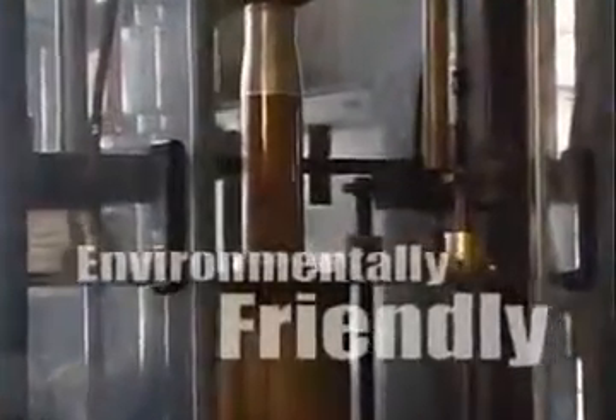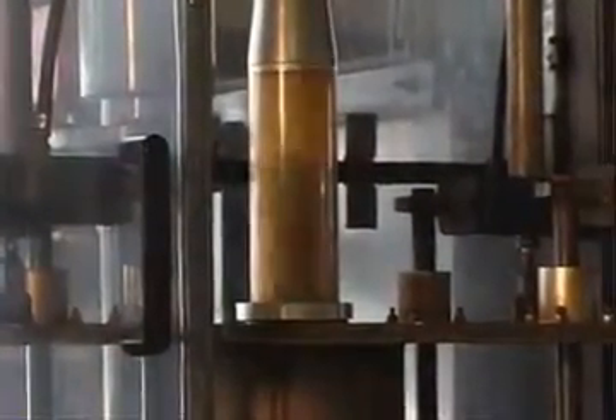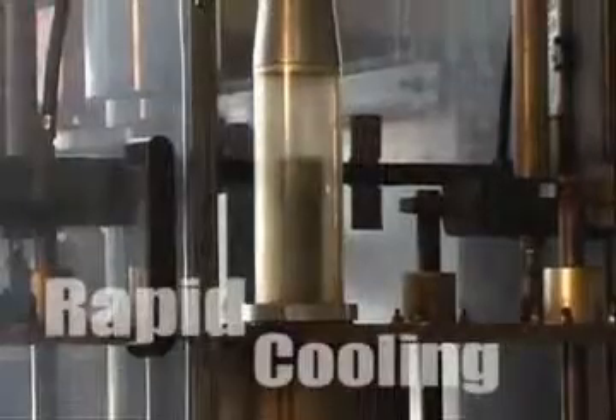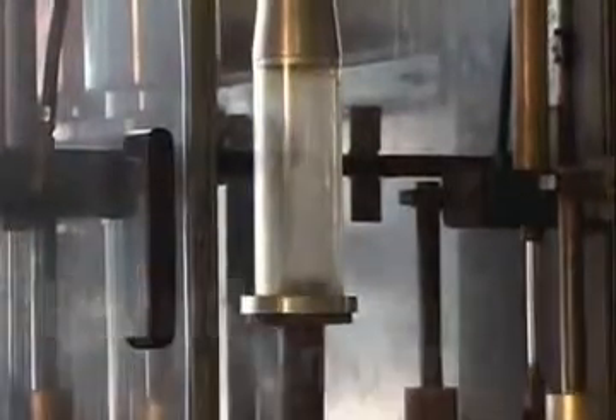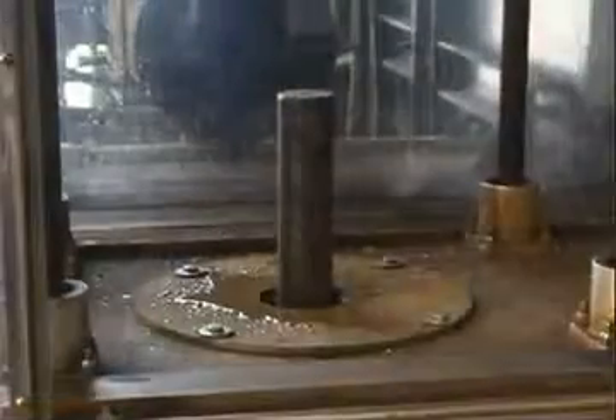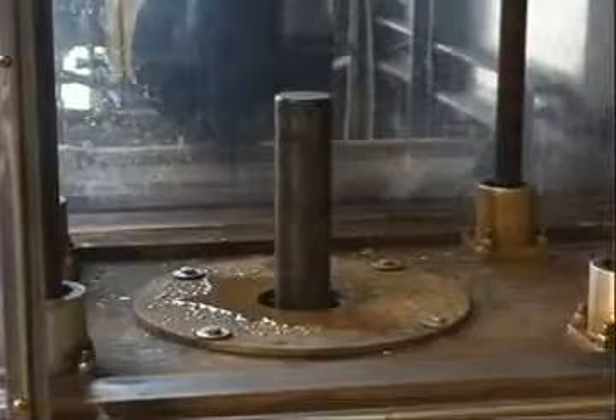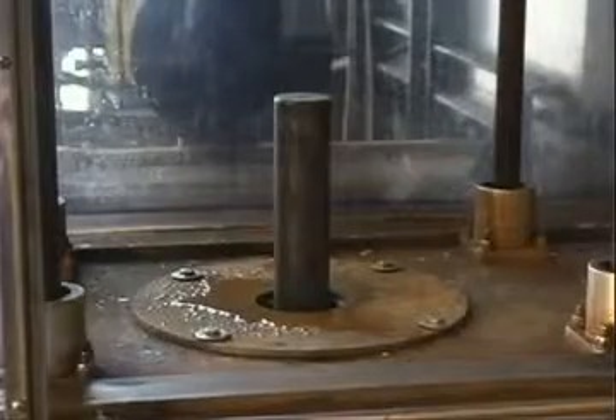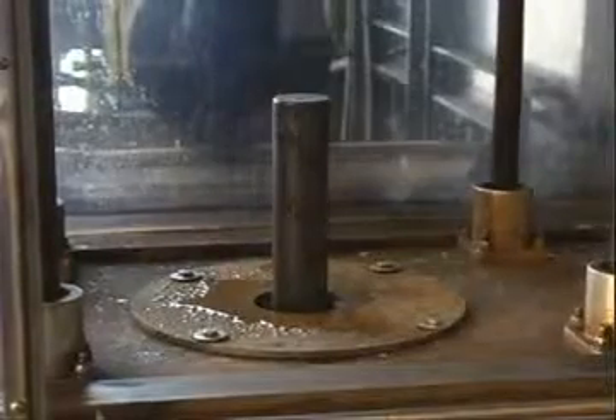IntensiQuench is an environmentally friendly, interrupted quenching technique for the heat treatment of steel parts. The first step is very rapid and uniform cooling from the austenitizing temperature, usually in highly agitated water, until optimal compressive stresses are attained in the surface layer of the part. Once optimal compressive surface stresses are attained, the part is removed from the quench and the final cooling step is done in air or inert gas.